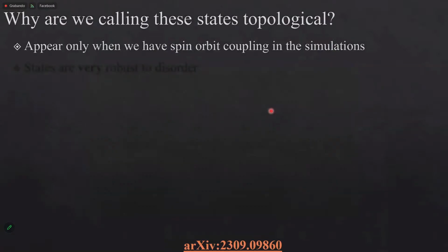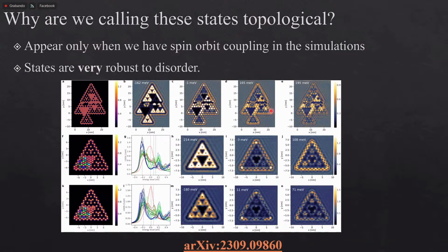And aside from the fact that these states need to have very high spin-orbit coupling, if you look at the literature, bismuth is predicted to have a topological state. So basically, when you have a fractal, you're creating more holes in it, so we expect this state to be topological. Also, there is something that, at least theoretically, you could investigate: the effect of disorder on these states and how robust they are. This we did using the bismuth tight-binding calculation because we had more freedom to look at disorder.